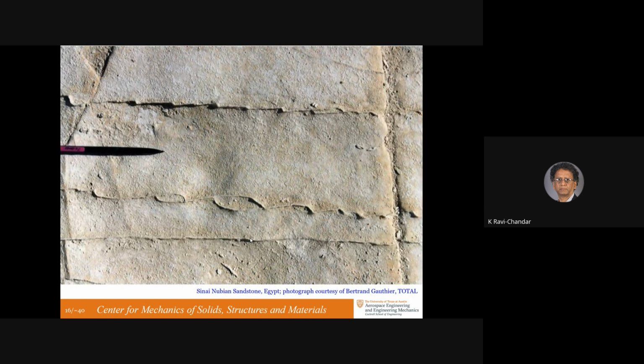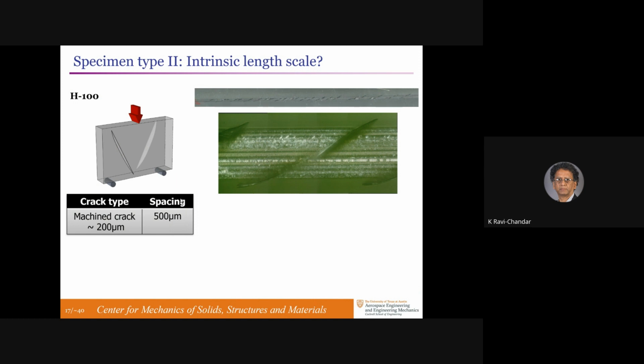Here are some traces from a sandstone. Parent crack is somewhere behind the screen. It's coming into the plane perpendicular to the screen. They're all slanted, and eventually they do the handshake to link up with each other. And this is the mechanism by which these echelon cracks are able to form, but there's no criterion yet about the spacing between them. So we redesigned the specimen to have stable crack growth over multiple distances in order to be able to see how these cracks interact with each other.